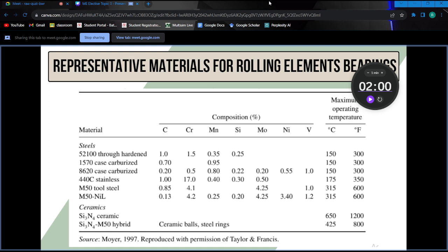As operating temperatures exceed this range and approach the final stabilizing temperature for the steel, the small amount of retained austenite phase transforms into less dense martensite, with an increase in bearing dimensions and with some loss of fatigue strength. Case carburized bearings are usually limited to an upper operating temperature of 150 to 175 degrees Celsius. M50 tool steel and M50 NiL are commonly used for temperatures above 175 degrees Celsius under severe conditions encountered in aircraft jet engines.